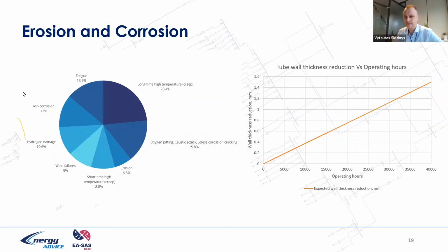And so erosion and corrosion: when we look at the distribution, long time high temperature impact comes from flue gas recirculation and fuel supply control. Ash corrosion is related only to the fuel. Welding failures would be related not only to welding condition, but also to temperature and dynamics in general, hydraulic dynamics. Short time temperature is still temperature. Erosion is still a high rate of mass flow, and oxygen pitting and cracking would also be true corrosion effects.